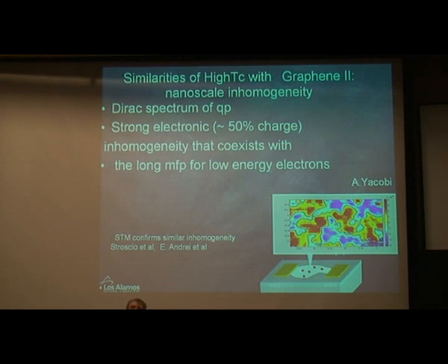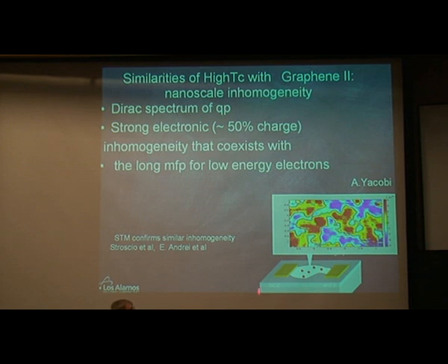Now, as opposed to high-temperature superconductors, probably the reason here is benign: this flake is sitting on the surface of silicon oxide, and it has a lot of charge inhomogeneity in the silicon oxide because of dopants and defects in the silicon. So what you see here are probably the puddles of charge that accumulate in certain regions just to screen out the effects of the Coulomb impurities.